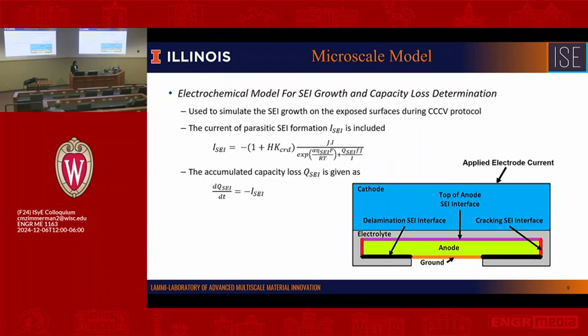For the electrochemistry model, the major failure mechanism we are trying to capture is the SEI layer growth. SEI layer growth will happen whenever we have a surface of the electrode exposed to the electrolyte. The size of such surface will be determined by the mechanical failure. So whenever we have a crack, or whenever we have a delamination, we're going to have new surface created, and that's where we can have SEI growth that will induce the battery degradation.